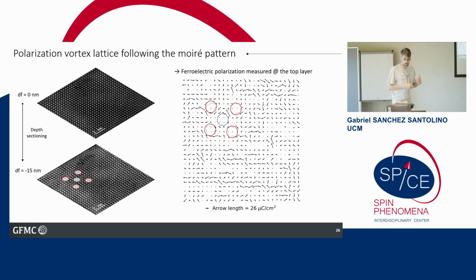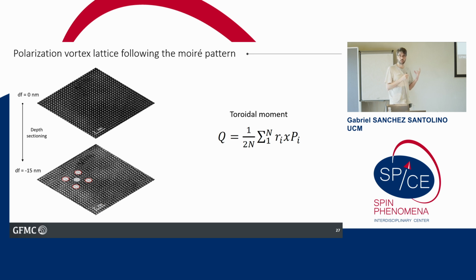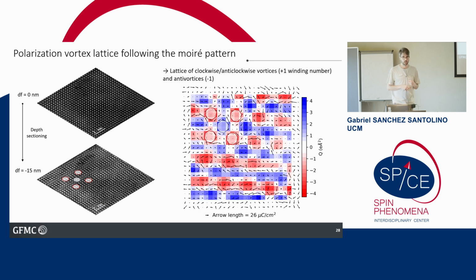And if we calculate, just to make it a bit more clear, the toroidal moment of this vectorial field, which is basically just the product of the position of the dipole by its ferroelectric polarization, we can visualize this toroidal moment, which is something like this. And now we can start understanding a bit what we have here. We have the positive vortices, which are the blue ones, and the negative ones, which are the red ones, with clockwise and anti-clockwise direction, both with a +1 winding number, and in the middle we have these anti-vortices.